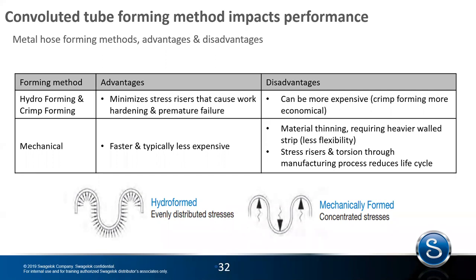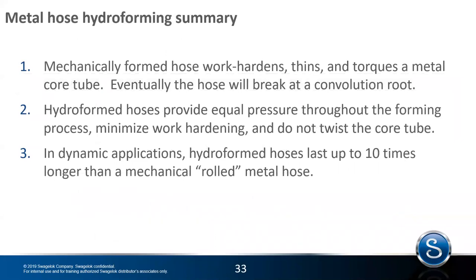So there's no twisting of this core tube of a hydroformed hose, but it takes longer to do it. So it's a little bit more expensive, similar to the sintering that Aaron explained. This is a more costly way to make the hose, but it will last far longer in a dynamic application. Actually, what we see with the hydroformed hose is the roots aren't what fails. It is actually the crest of the convolutions that wear away because the metal braid rubs against the hose in a dynamic application to the point where it rubs away the crest material and fails about 10 times longer. So if you get, for example, 10,000 cycles out of a mechanical formed hose, what our experience is the hydroformed hose will last about 100,000 cycles and it will be a different failure mode.